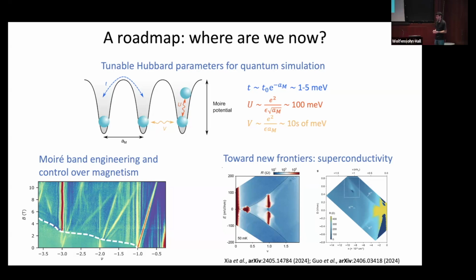Now this is great for thermodynamic gaps, but it's not good for spectroscopic gaps. So if you think about what happens in a superconductor, charge can still move. It can still screen the electric field that you're applying with the backgate underneath. So basically, for us, it's very difficult to distinguish between a metal, which is screening, or a superconductor, which is screening. So it's not clear to me that we would see such signatures of superconductivity at all. These are at much higher twist angles than what we were looking at also. So it's a different regime of parameter space too, which may or may not play a role. We have been thinking about possible experimental signatures of superconductivity in compressibility measurements, and I think it's a really exciting direction to pursue, but I don't have anything experimental to say about it at this point.